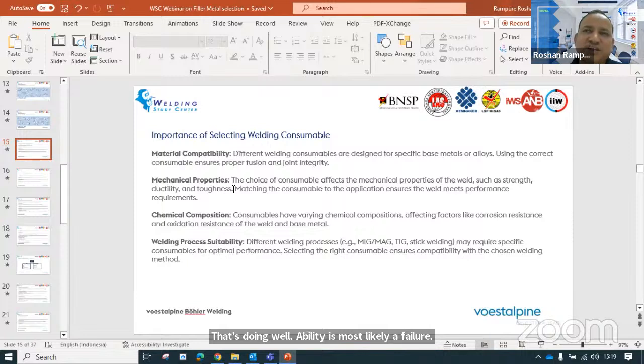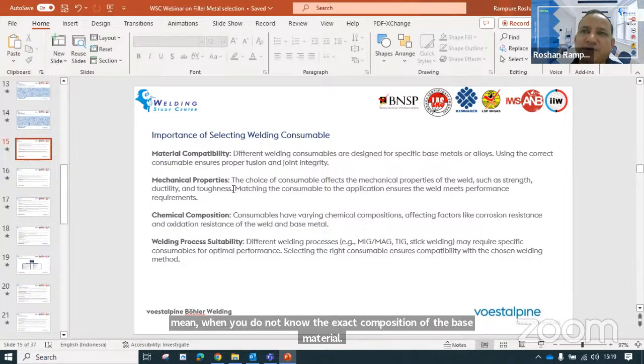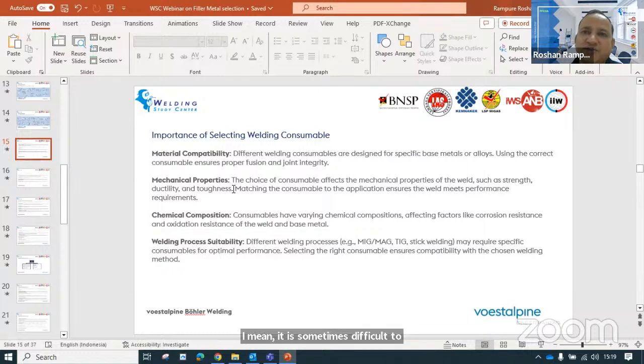See, in such a case, when you do not know the exact chemical composition of the base material, it is sometimes difficult to select a suitable welding consumable. So there are two options. First, you do the chemical analysis of the base material itself and determine what type of base material it is, whether it is unalloyed material, low alloy material, what alloying elements are present. When you get the chemical composition of the base material, then you select a suitable welding consumable which closely matches the chemical composition and the mechanical properties of the base material.